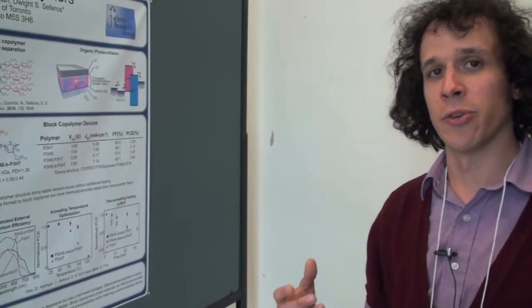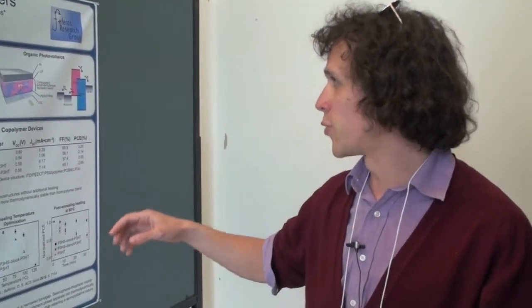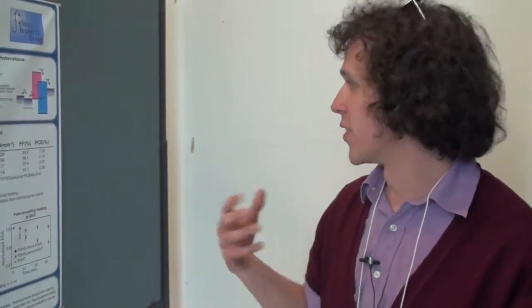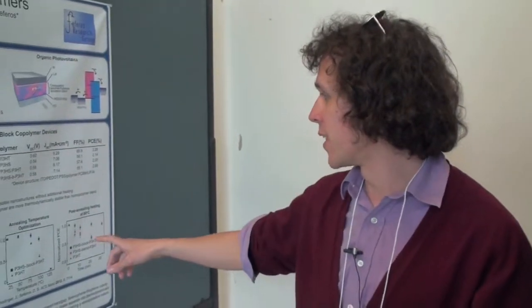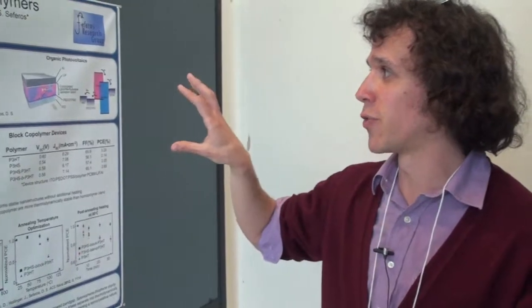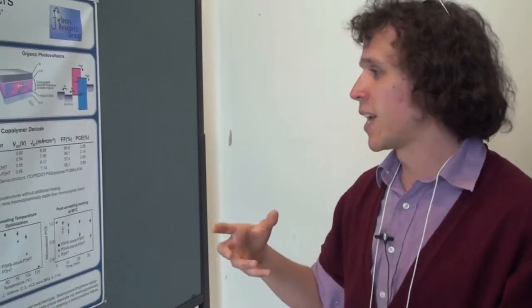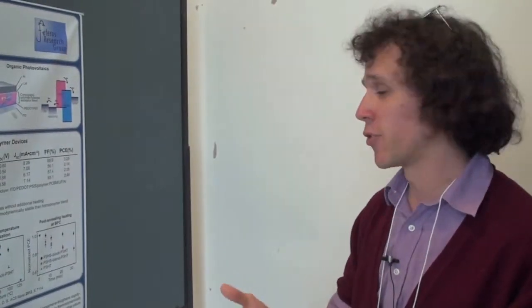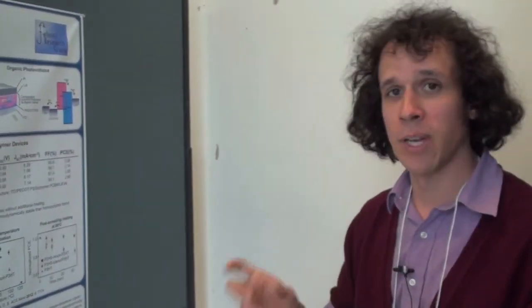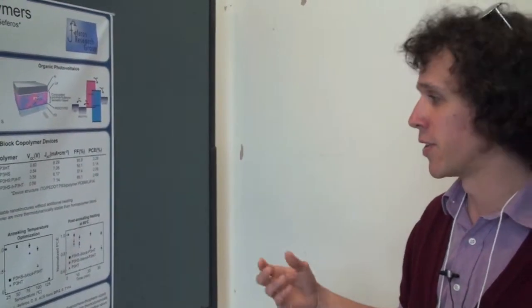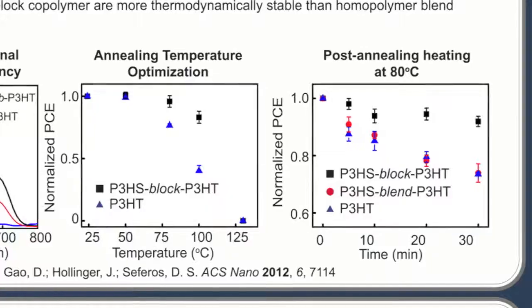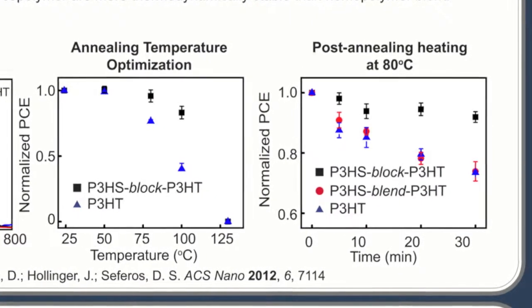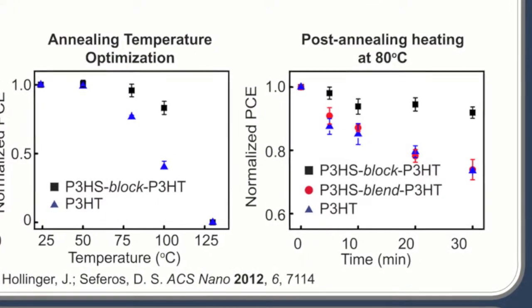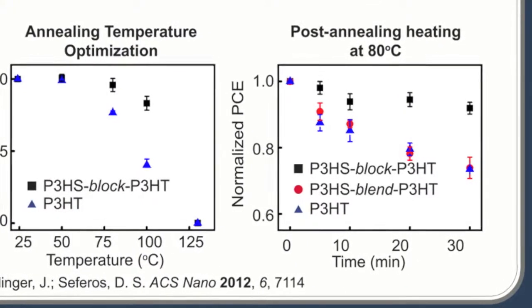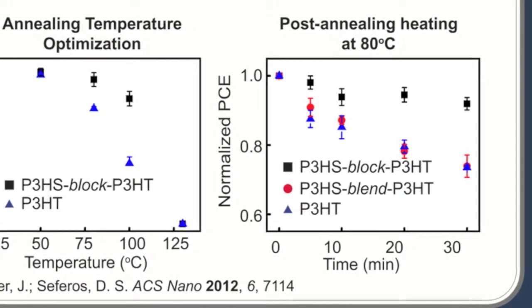And the long-term stability was also something that we investigated, and we found that once we fabricated the device and annealed it at 80 degrees after fabrication, it seemed like these structures formed by the block copolymer with the PCBM acceptor, that morphology was more stable than it was with either P3HT homopolymer or just a physical blend of poly-3-hexyl-selenophene and poly-3-hexyl-thiophene homopolymer just blended together. So again, the relative decrease in device performance with this post-annealing step affects the block copolymer much less. So it says that these structures are more stable overall.